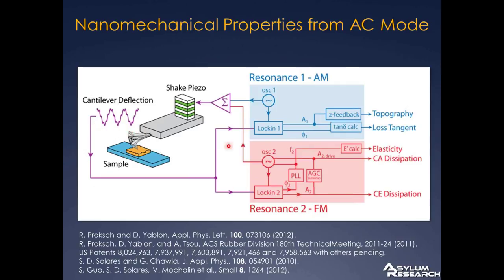That signal goes back. Again, one signal is analyzed in the first lock-in, and then the second lock-in is tuned to that second, higher frequency mode. I won't go through all the details here, but we run it in something called a phase lock loop that keeps it at its resonant frequency. The output of that, this resonant frequency, tells us about the tip-sample stiffness, or I labeled it elasticity here.